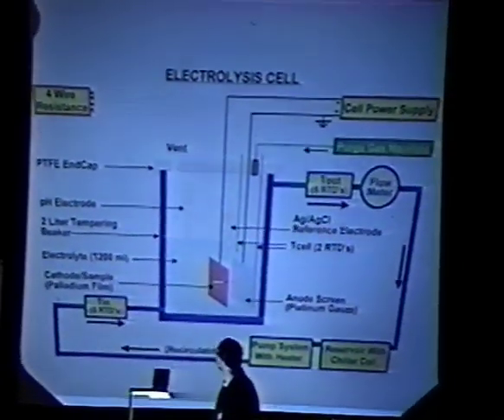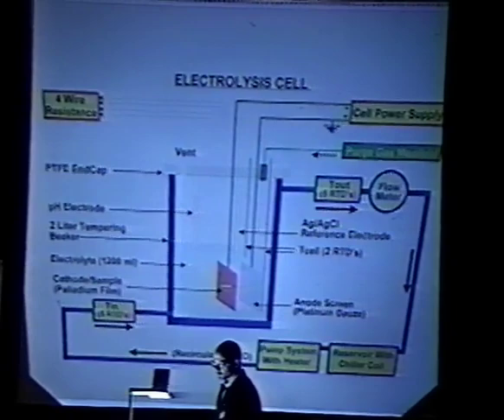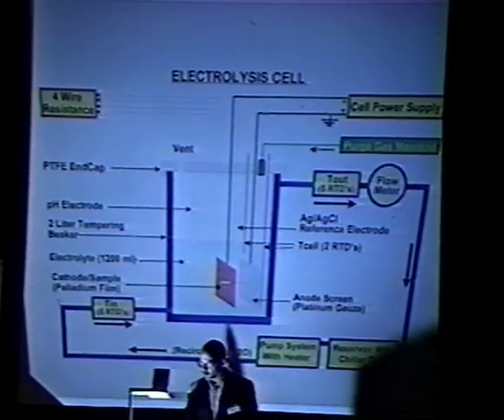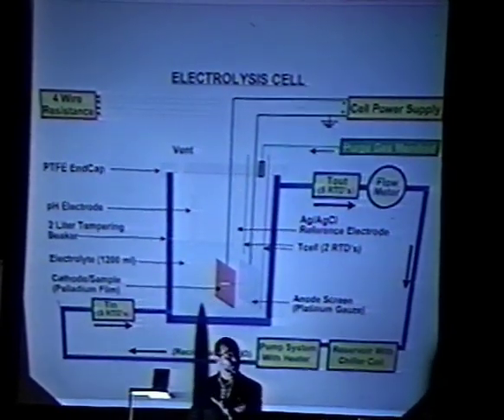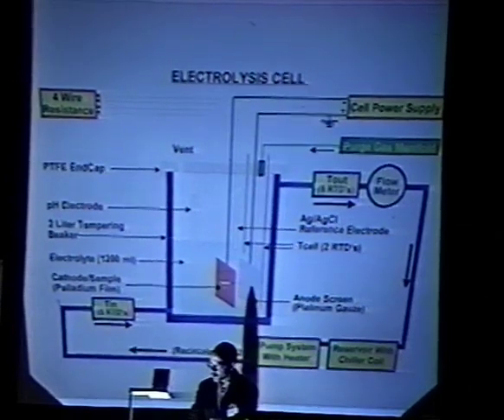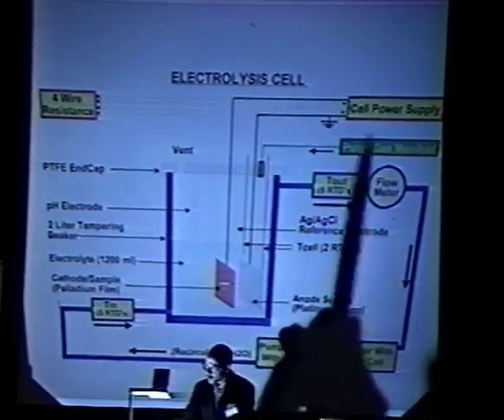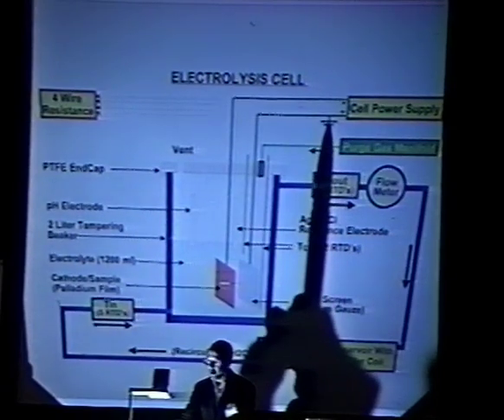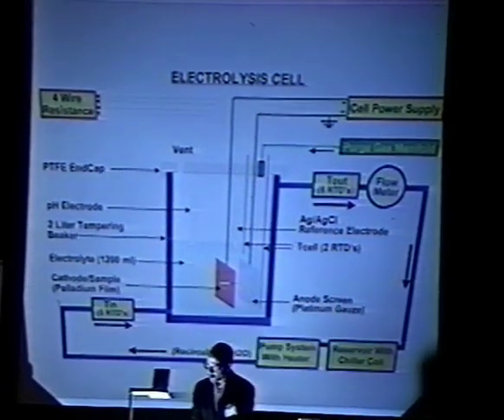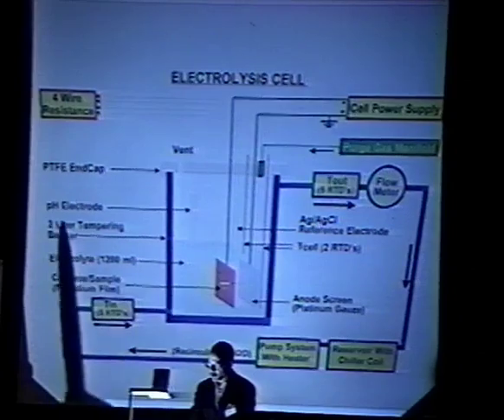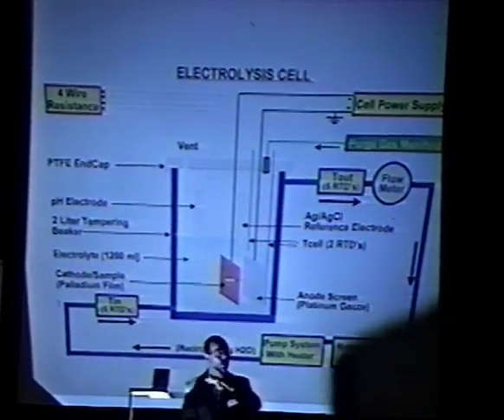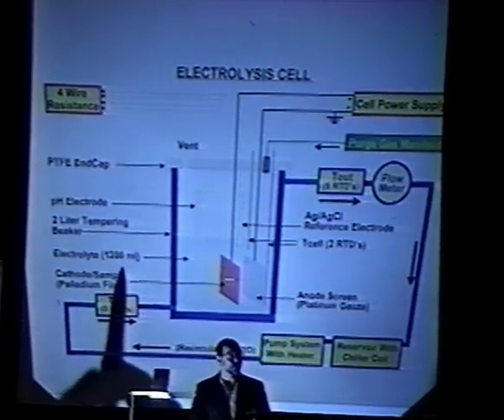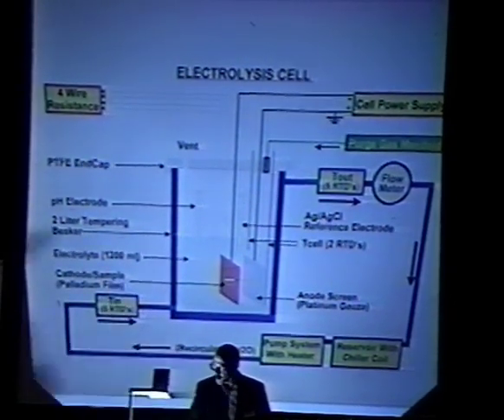But this is probably the biggest overview type of figure of the system. What you can see, I guess the two main things, of course, is the cathode, which is basically located centrally near the bottom of the cell, and there's the anode. I typically bias these with a DC power supply, and the anode is tied to ground at one point there. This whole system is set up with a 2-liter tempering beaker. It's quite large, so that when I fill it up with solution to cover the electrodes, it's about 1,200 milliliters of electrolyte.